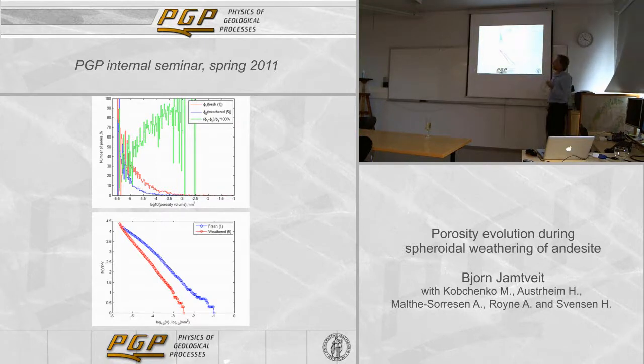During the weathering, because we close the big pores, the cumulative distribution of pores gets much steeper. So the weathered rock has much fewer big pores, but they catch up again with the small pores, and it has a much steeper distribution than we normally see in magmatic rock.